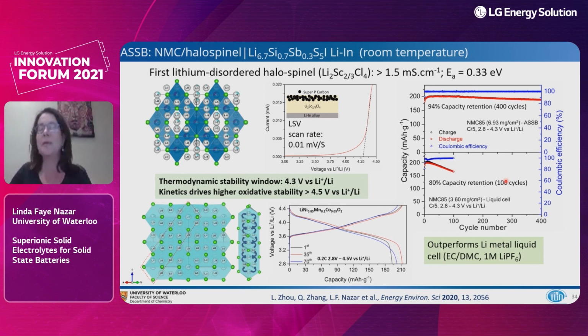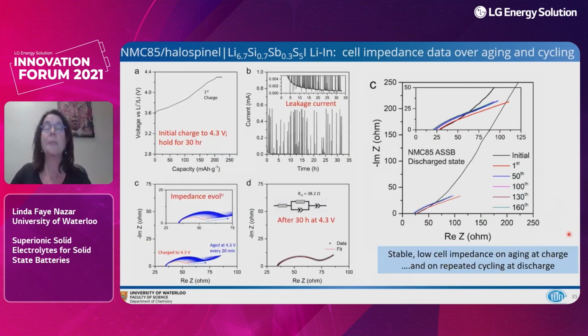It's really not maybe a fair comparison, but there's no additives in this cell. It's just a plain vanilla electrolyte. But you can see that the difference is really quite surprising. And well, it's not surprising, but it's promising. And we've also carried out impedance studies to try to understand the origin of this really good performance.